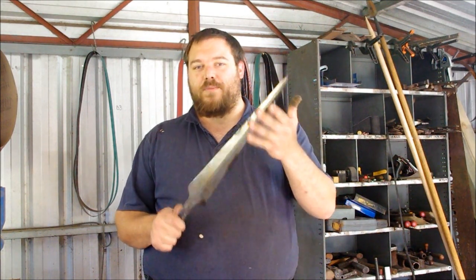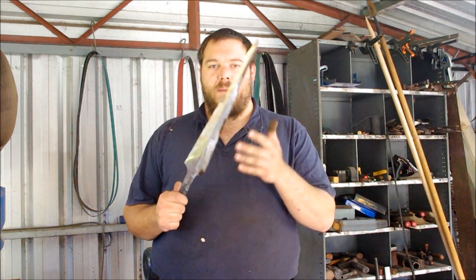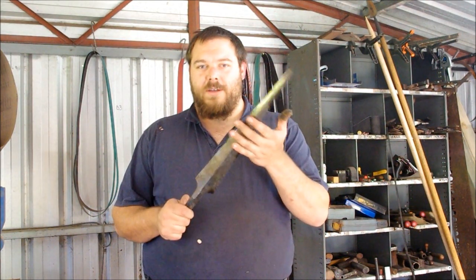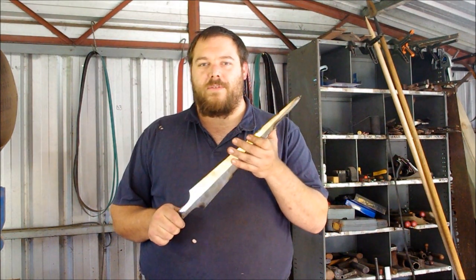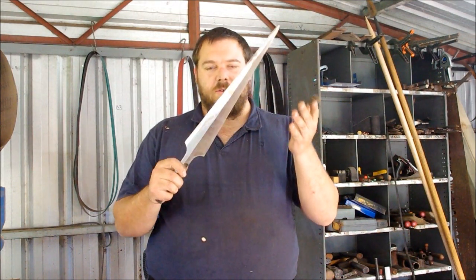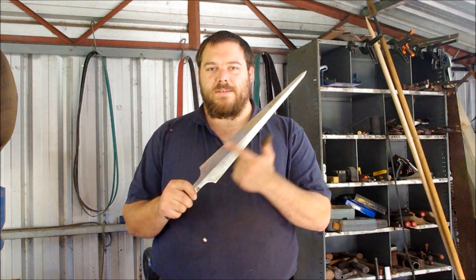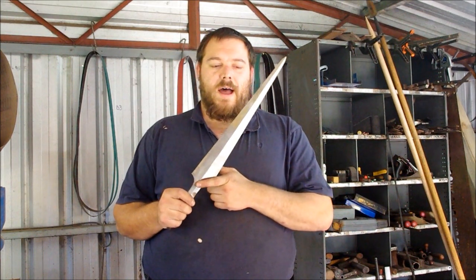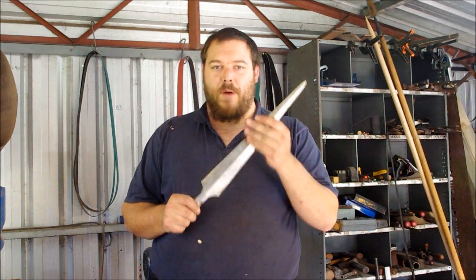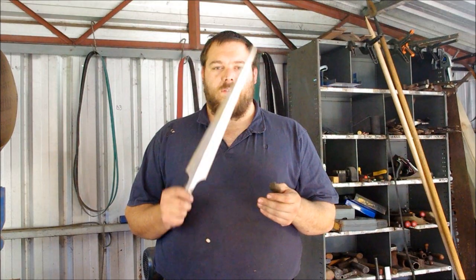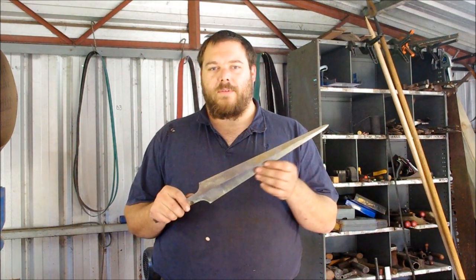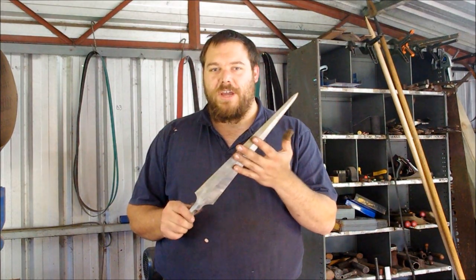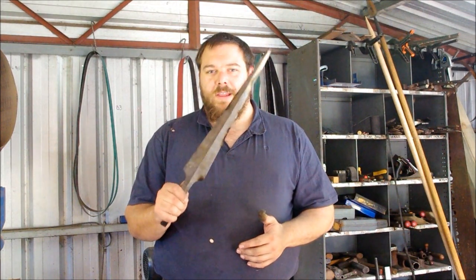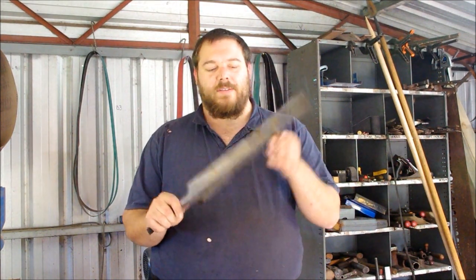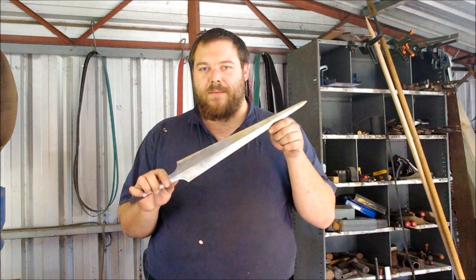But obviously because this is pre-heat treat grinding, I don't have to worry about it being detempered or anything like that. But because it was getting blunt to the point that I couldn't remove sufficient material, I switched over to a sharp belt, and you can see that the lines are much crisper, much cleaner. And this is really important for when you come to the post-heat treat grinding. So once you've heat treated your blade, you really want to be able to remove material without putting in too much heat, and you don't want your blade ending up looking like this after the heat treat. So a fresh belt is really important.